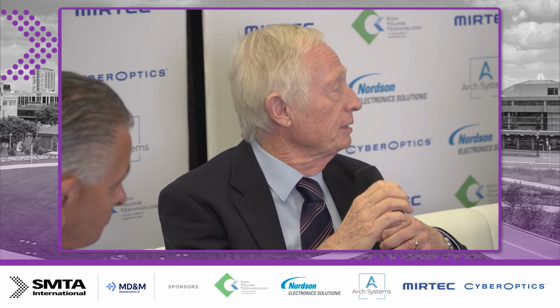The hybrid joint you're talking about, I don't know what your opinion is, but I have a feeling the hybrid joint is not going to survive. It's got too many issues. If you go back to the days when we were phasing in lead-free, for a while you had packages with lead balls reflowed with a lead-free paste. And in the end, they found that the only way to get reliability was to take it to a temperature where the whole thing melted and you had a homogeneous joint.